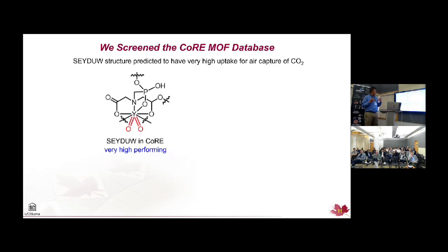And like many people, we also screened the CoRE database, and we screened it for direct air capture. We did the calculations to get charges on this, and we had this hit called SEYDUW, which is just a reference code that the CSD gives a structure, but that was from the CoRE database, which is supposed to be clean. And it was very high performing. I was a bit surprised, but nonetheless, that's great. But then we looked at the structure and saw that the yttrium was in a +7 oxidation state, which is actually impossible, because it doesn't have that many valence electrons to give away.